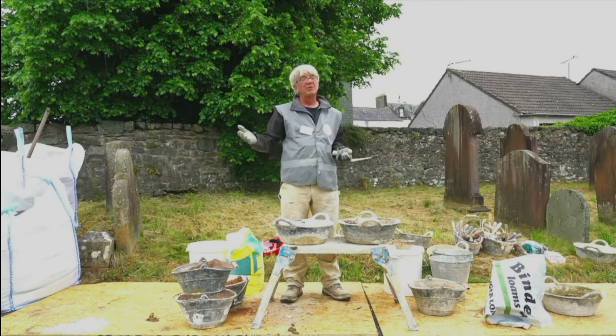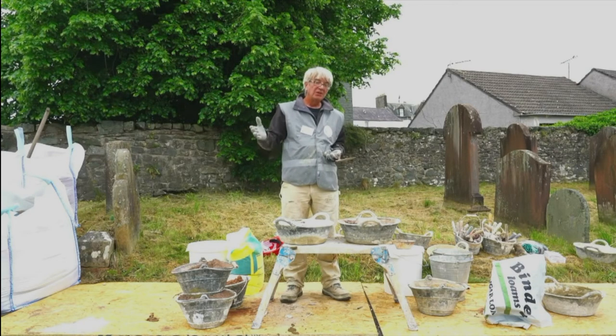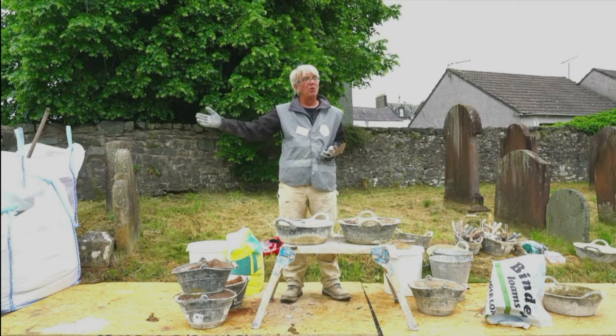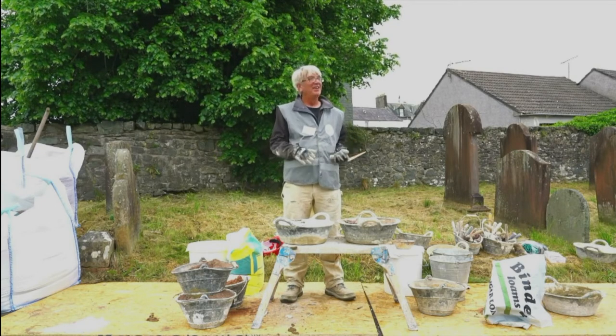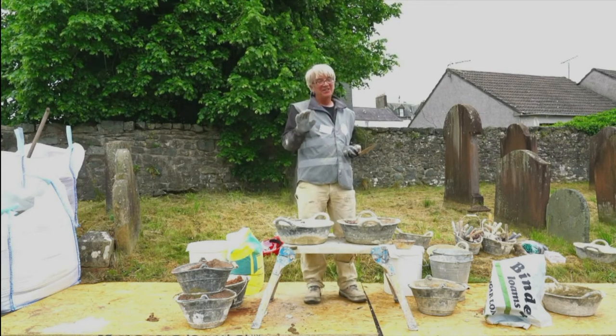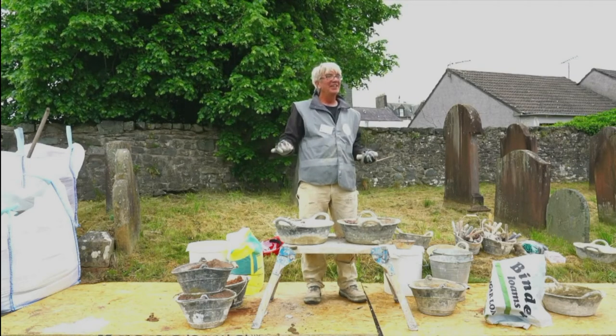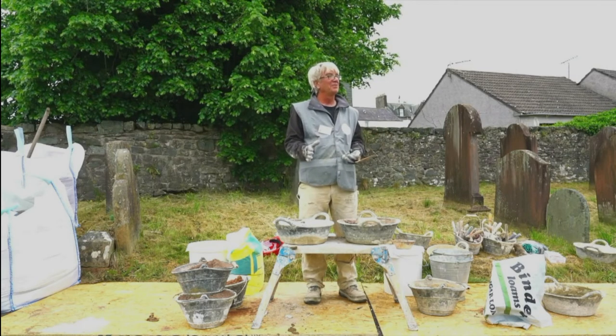And it was fine. It slaked within about 10 minutes, I suppose. It was powder. And it went on. Shrinkage cracks, day one. Okay, close them down. Shrinkage cracks, day three, day four, day five, day six. And 4 months, and in the end, I was going around, thinking, oh, for goodness' sake, I wish I'd used pure lime. And still, it's still late slaking a year later. I can see under the little bits of lifting off this material a year later. And I thought, oh, for goodness sake, that's the problem. And that's another reason why you wouldn't use natural hydraulic lime for these purposes.